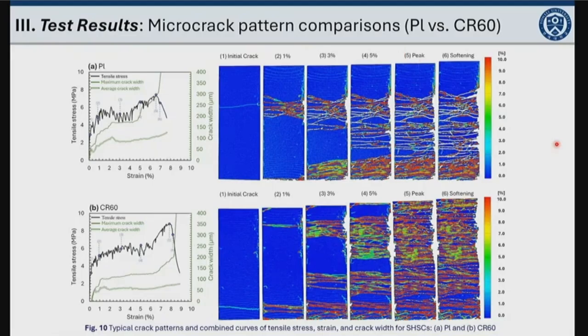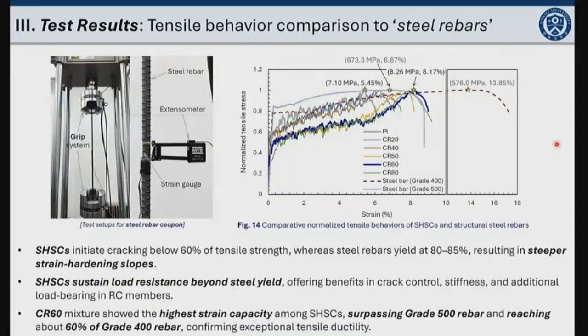This verifies the benefits of using crumb rubber in terms of decreased matrix crack tip toughness and increased crack bridging effect. And this is the comparative normalized tensile behavior of the strain hardening cementitious composite developed in this study, and the commercial steel reinforcing bars, steel rebars.